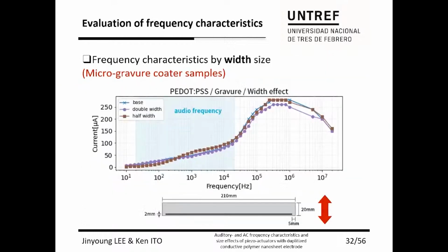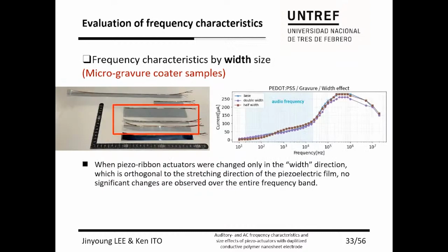First, we changed the size in the width direction, which is orthogonal to the stretching direction of the piezoelectric film. We prepared half and double width samples from a standard size and measured their frequency response. From the results, there were no significant differences between samples over the entire frequency range.